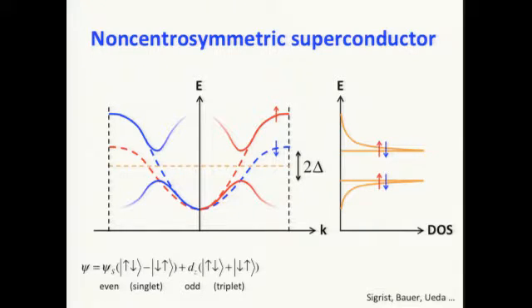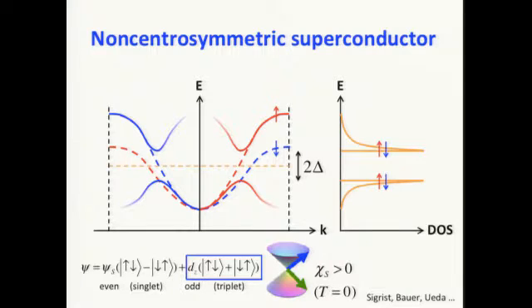Furthermore, the wave function of the Cooper pairs can be written down as a mixture of a spin singlet component and a spin triplet component. A very nice way to illustrate the quantum mechanical spins of the spin triplet component is that even in the out-of-plane basis, it has zero angular momentum. When you project the two spins in the in-plane basis, it actually has a finite spin angular momentum. What it means is that even in the zero temperature limit, the spin susceptibility of this triplet pairing component is bigger than zero. It's non-zero in this case.